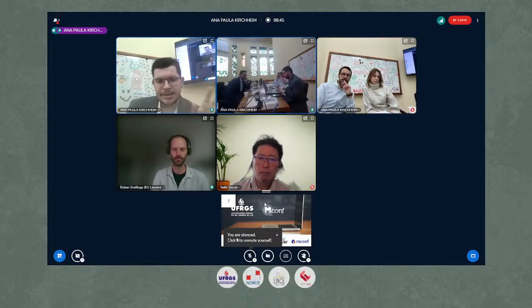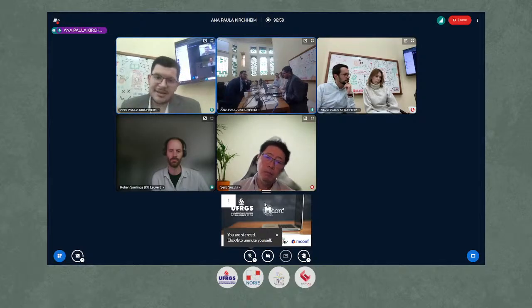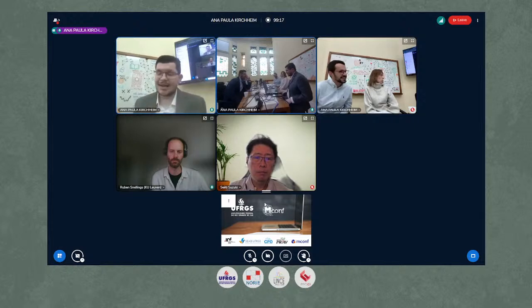But these results I will redo again, because when we went to the synchrotron XRD, they were still processing the software to process the data and form the X-ray diffractogram. And we were one of the first users in the line, so the algorithm, the software was not good enough. So our X-ray, especially at low angles, is not good enough. Like the gypsum peak is quite weird and this kind of thing. And I was waiting for them to solve these problems to have better diffractograms. And they gave me a yes signal like 1 month to 1.5 months ago. And I couldn't do it for the defense.